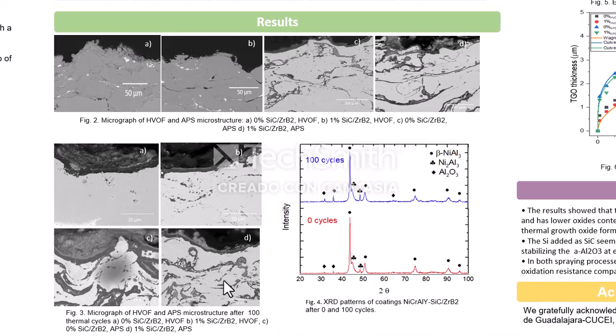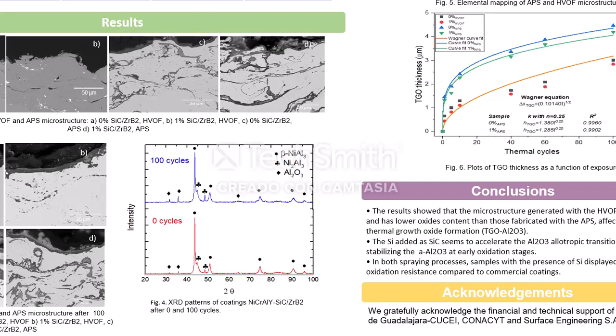This micrograph shows the microstructure of the coating system after 100 cycles. In both processes, the thermally grown oxide was observed, along with internal oxidation of the coating. The TGO appearance is similar in the APS and HVOF coatings, also with internal oxidation. The X-ray diffraction results reveal the presence of the TGO layer in the samples, also the presence of the beta aluminum nickel phase and a secondary phase, which are normal to be present in this type of coating.